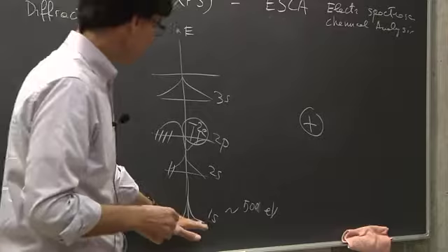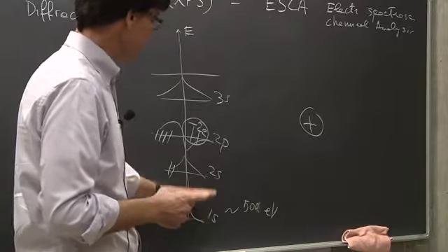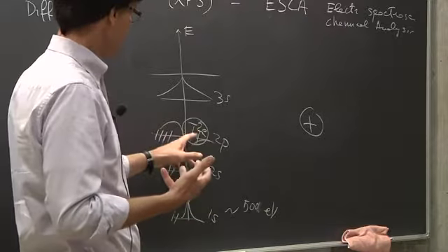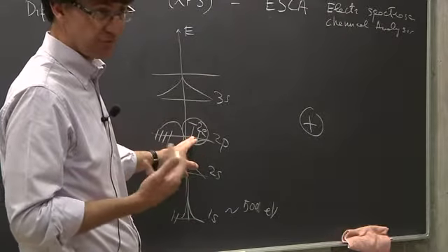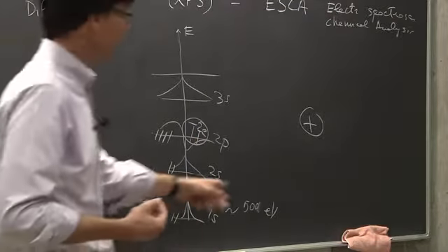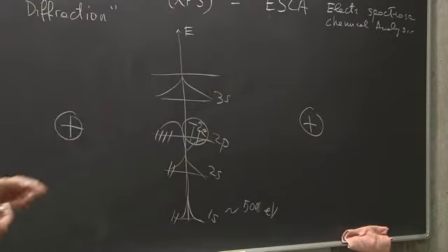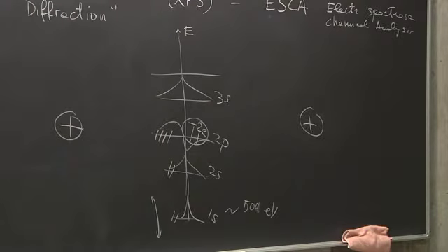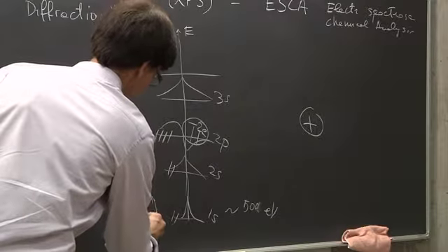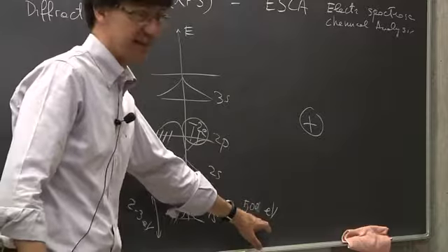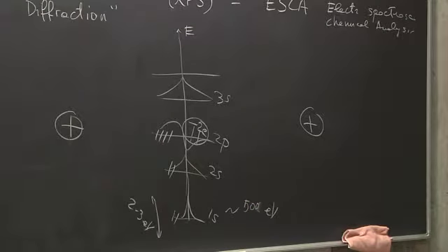All right? So the position of the electrostatic potential of this 1s state depends heavily on the charge state, on the valence state of the oxygen itself, and also on the position, distance, and charge state of the nearest neighbors. And the changes due to this electron transfer can be of the order of 2-3 electron volts. Of course, this is very small compared to the binding energy of the 1s state, but it's still not negligible.